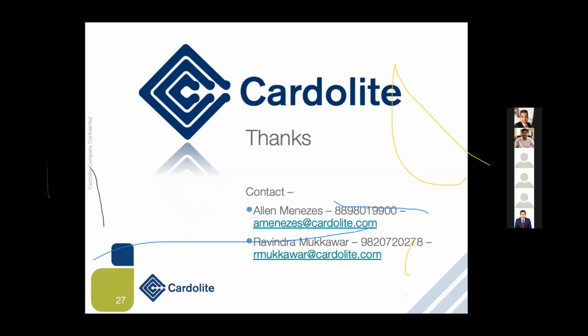Actually, regarding your problem with the marker pen, I'm Dikesh Patel. Your curing is not proper. The marker pen mixes with that system, and your curing time is long. You say 7 days, but actually your curing time is almost 21 days. When you mark it and rub it after 21 days, it means your hardness is not properly done. Your system is not hard properly.